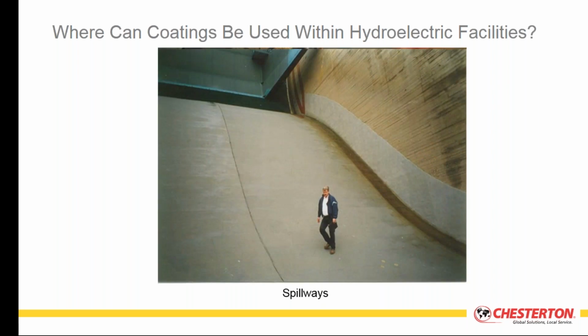Finally, we look at the actual spillway structures. Above the spillway, you see the tainter gate or radial gate. When those gates are opened due to high dam levels, the flow of water passes very quickly across that surface and causes erosive damage to the concrete. Concrete is chosen not for its abrasion or erosion resistance, but based on its cost and structural strength under compressive loads when reinforced. It's not a highly abrasion-resistant material. So in those instances, it might be beneficial to apply a more erosion or abrasion-resistant coating on top of the concrete, particularly in high-flow regions. As you move up the walls where flow is less pronounced or the velocity and impact damage is less pronounced, then you don't need to use a coating.